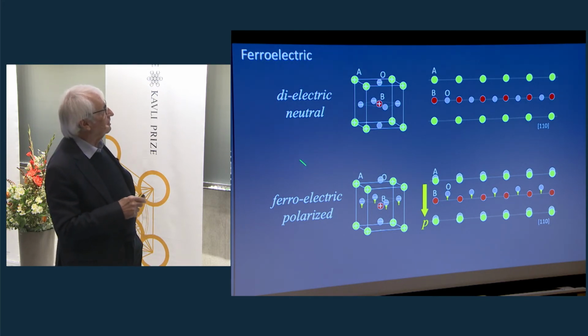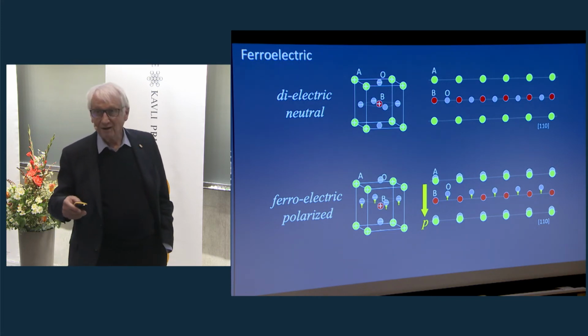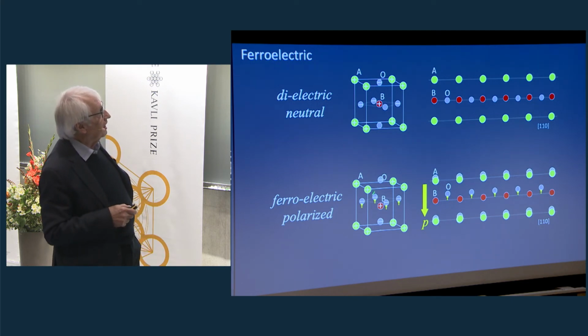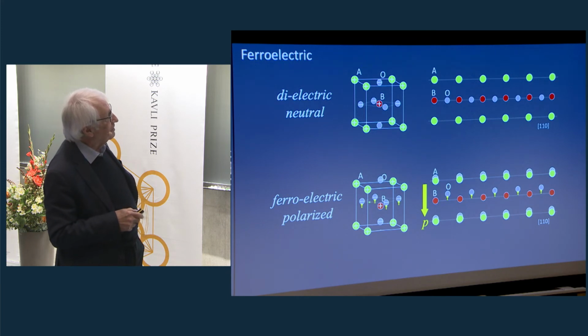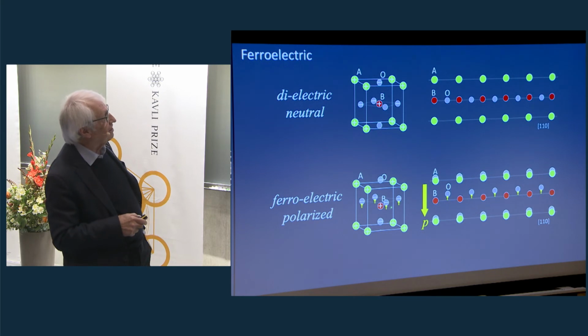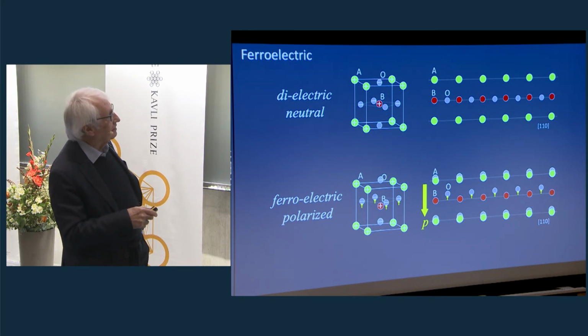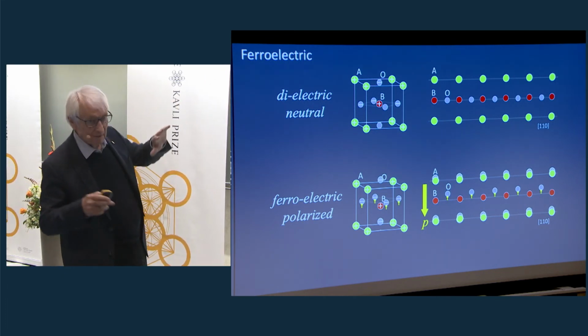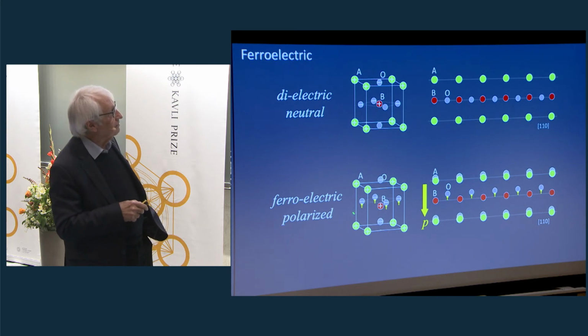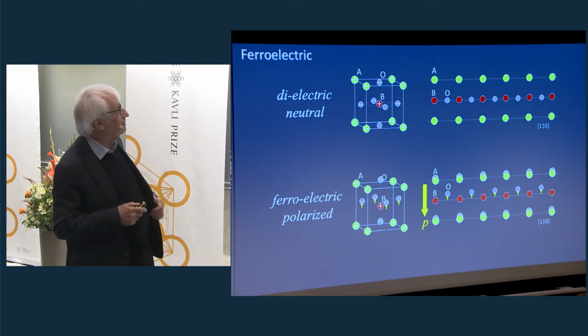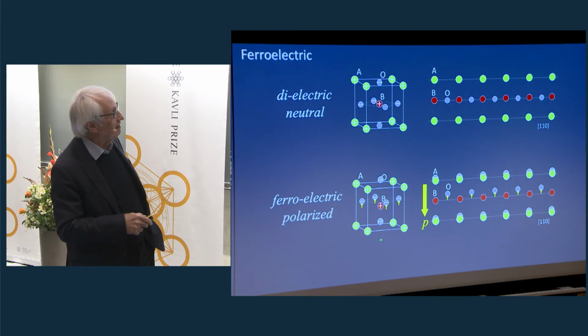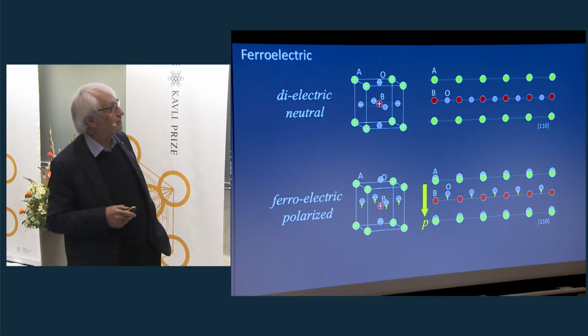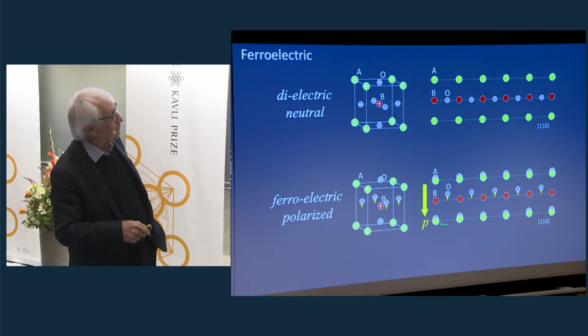In a ferroelectric material, you have all kinds of atom rearrangements. In our following case, the oxygens have shifted upward here, so that the center of gravity of the negative charge has moved upward, while the cation lattice in a first order has remained untouched. So we have here no agreement between the 2 centers of gravity. So we have on the unit cell level a charge distribution, and in this case then a polarization, a dielectric polarization. We again are looking along these projections as before, and we see here the oxygen atoms shifting upward in this sketch.